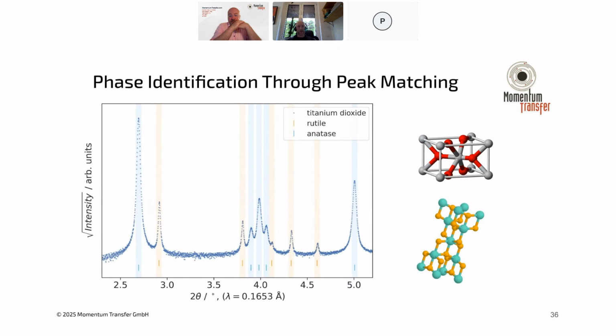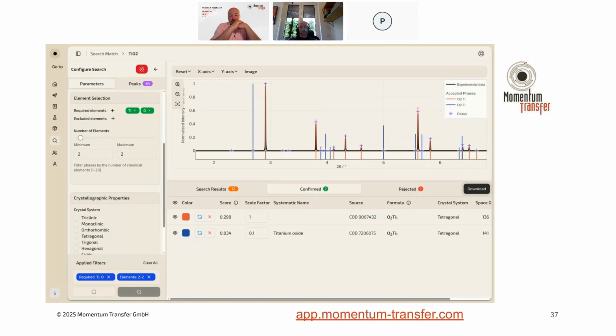So from a detection perspective, again, we have fingerprints of certain peak positions and relative peak intensities that come from different phases. In this case, we have titanium dioxide, rutile and anatase, and I've highlighted them in different colors in this pattern. So you can very clearly see the presence of these two components in this mixture and identify them from those peak positions.